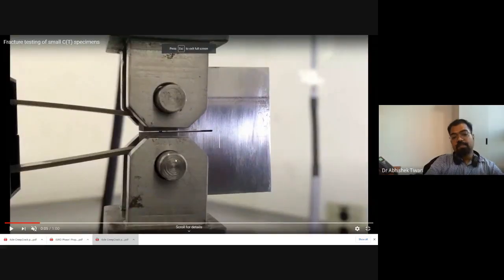As we have discussed, this is a compact tension specimen. This part is a clevis, which is holding the specimen. So this is the specimen, and you have two pins which are connected. There are two holes in the specimen through which these pins are passing. And this part is called the clevis, which is attached to the machine on the lower side as well as on the upper side. This, what you see, is called the clip-on gauge or COD gauge. So clip-on displacement or crack opening displacement. It measures how much the crack will be opening.